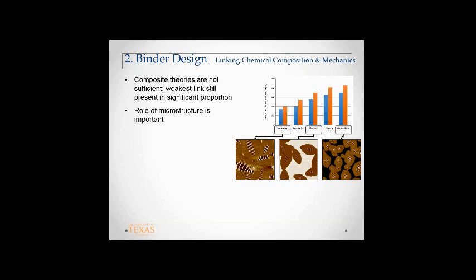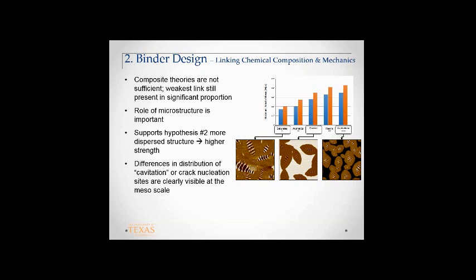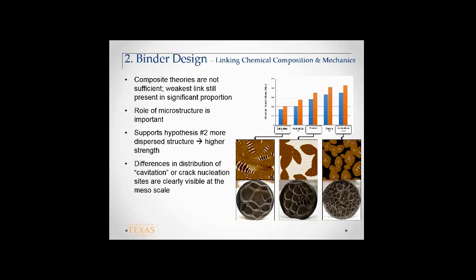So this ties to our second hypothesis: for saturates, you have these large structures. For these polar stuff, you have these dispersed structures. And sure enough, if you run a finite element analysis, you'll see that you have much higher stress concentration here, and much lower and more distributed stress concentration in these kind of systems. So this result supports the second hypothesis, and also these are pictures of the idea of crack nucleation in the form of cavitation.